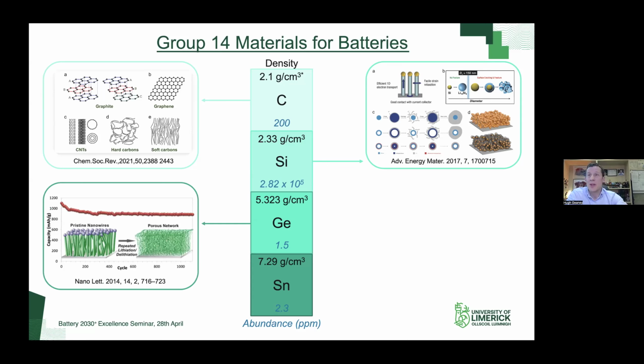Germanium is a material that keeps bringing us back in because it has some very interesting properties. This paper that I show here is actually from a colleague who is in the Chemical Sciences Department, Ty Kennedy, who carried this out during his PhD over a decade ago. And what he found during this study was that if he took a germanium nanowire electrode, what would happen during lithium-ion cycling is extremely long cycling stability. And what he found was there was this really nice porous network that was formed through material restructuring of the germanium. So germanium is a very robust material in terms of long-term cycling stability.